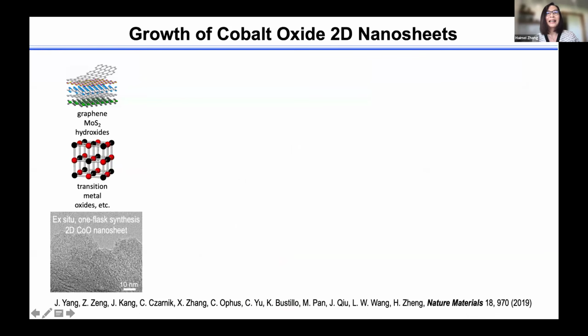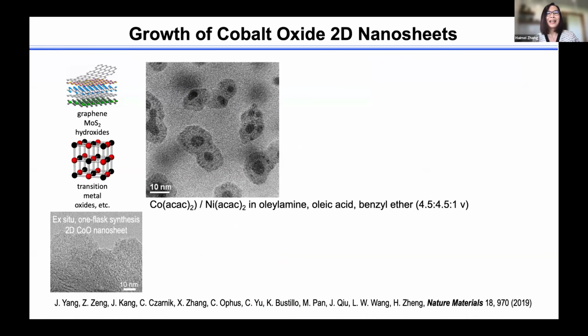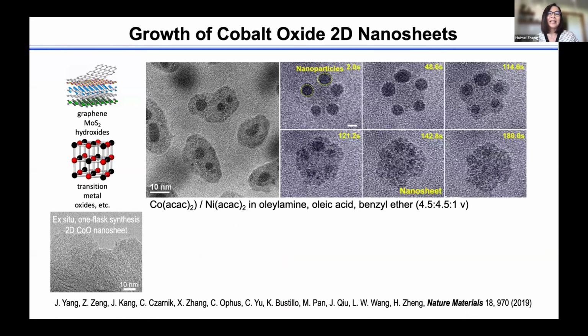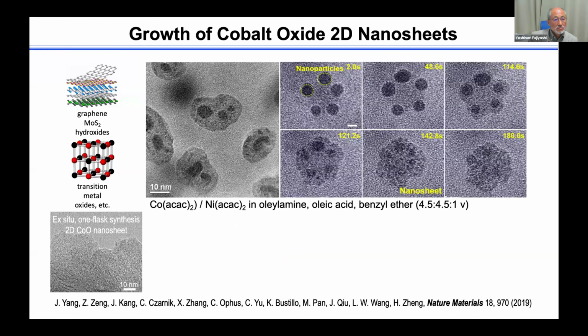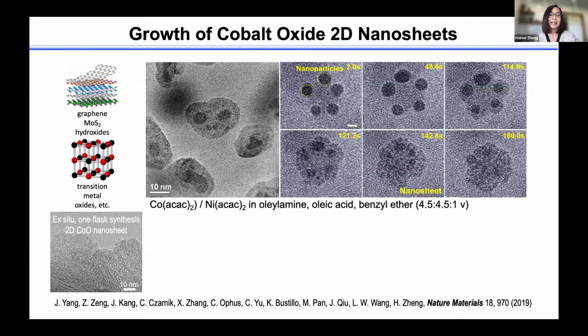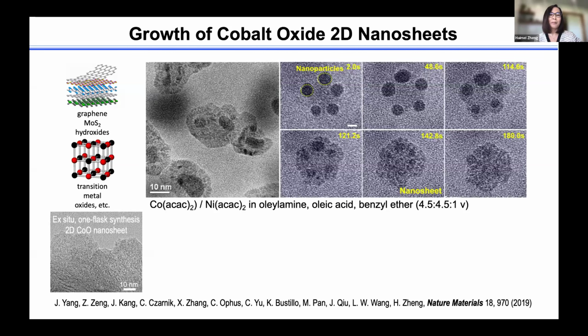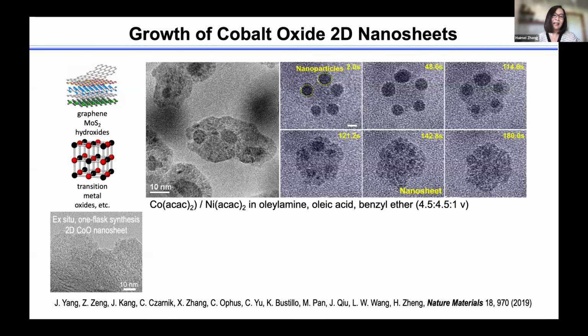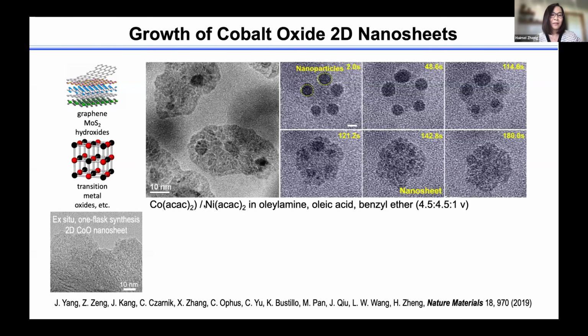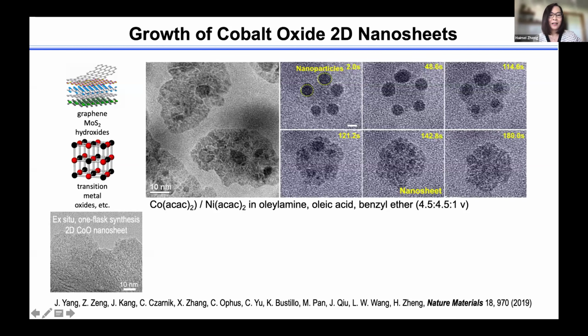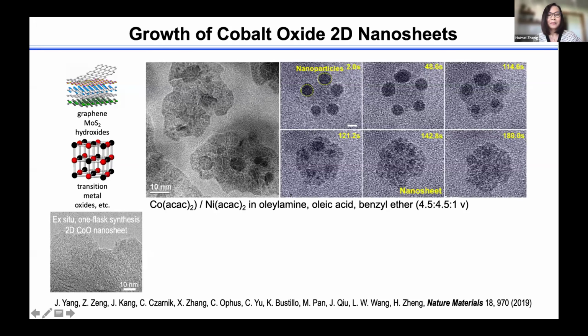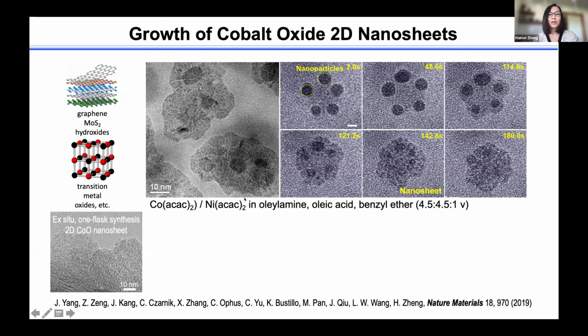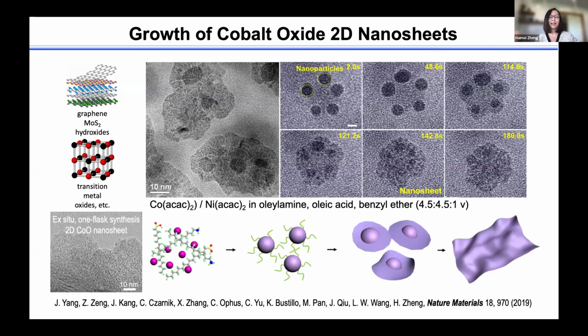And first, I'm going to show the example of 2D growth using 3D nanoparticles as intermediate. In this case, as you see, this is growth of cobalt oxide 2D nanosheet. We know many common 2D materials have layered structure in their bulk format, for example, graphene from the graphite, many varieties of metal hydroxide. For these materials, this 2D growth is more reasonable from thermodynamic consideration. Mostly these lateral growth can be faster because of the lower energy.